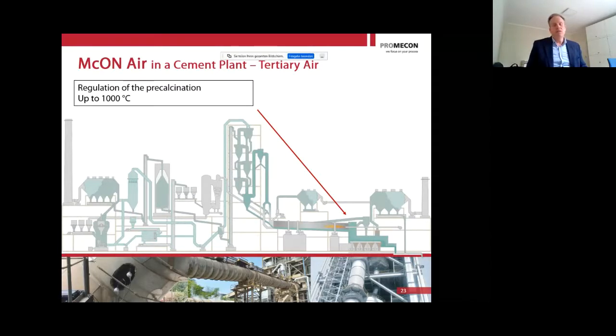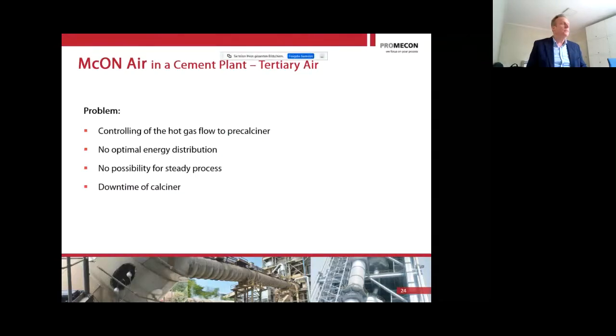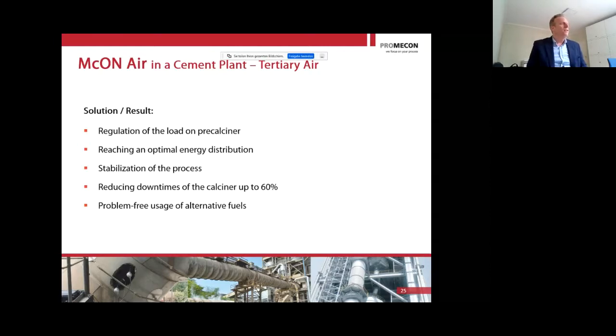So for that, you need a measurement. You need to know how much goes out through your TAD. So you would like to have an optimal energy distribution, you would like to have a steady process, and you would like to reduce downtime of the calciner. The solution here is, of course, a good regulation of load on the precalciner and a very good tertiary air flow that follows that load, right? And we have seen clients that have reduced their downtimes of the calciner up to 60% by better controls. So for some plants, tertiary air measurement is a key element also to availability. And if I see Indian plants which have a high load factor, high production factor, downtimes are certainly critical.